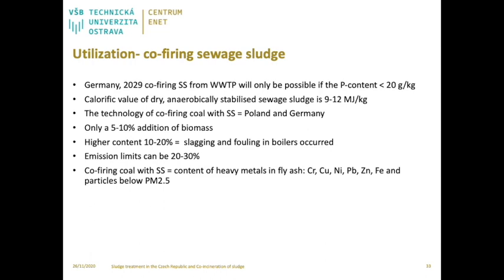Dewatered sludge contains up to 75% water, which is energy-intensive to remove. The calorific value of dry anaerobically stabilized sewage sludge is 9 to 12 megajoules per kilogram, while for food waste it reaches up to 18.5 megajoules per kilogram. The technology of co-firing coal with sewage sludge is used mainly in Germany and Poland, and is being tested in the Czech Republic. Originally, only 5 to 10% addition of biomass was used for large-scale coal-biomass co-firing power generation, because at a higher amount of 10 to 20%, slagging and fouling in boilers occurred. Emission limits for stationary emission sources can be met even with the addition of 20 to 30%.